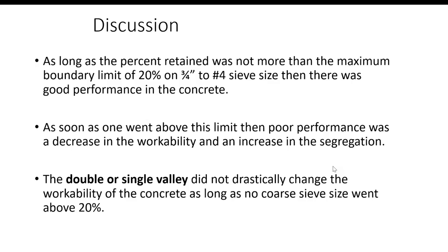Segregation started to happen. So pumpers, if you have too much of any one sieve size up here, this is when your life can get dangerous. When you have a whole lot of any one sieve size on the coarser size, that's when your life can get very dangerous.